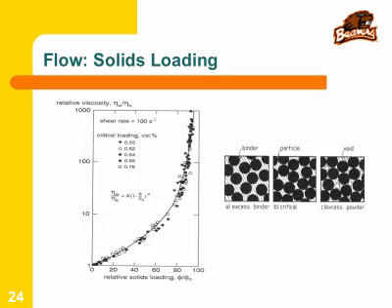Right? So you have some intermediate case where there is a small layer of polymer separating the powder surfaces, and it is now closest to the maximum packing fraction of the powder. And so that is the critical stage where the viscosity ends up shooting towards infinity. Right? There's a transition point between behaving like a liquid and behaving completely like a solid. Right? Solid, infinite viscosity. Right? If you look at the curve going up like that.